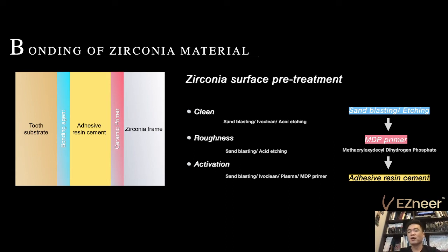very important, because zirconia without any glass crystallization, without any glass inside, cannot be acid etched to get a rough surface, and also doesn't have a reaction layer. So this is not good for the resin cement bonding, and also not good for the ceramic primer. So if possible, follow these three steps, and you can get good and enough bonding strength.